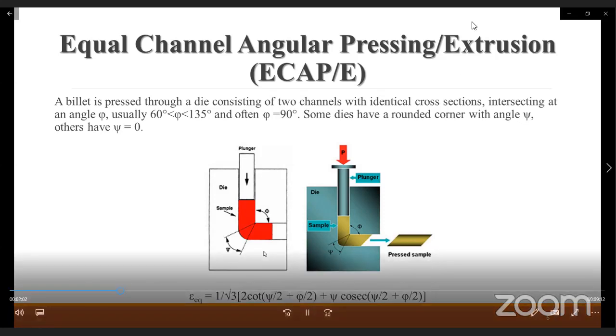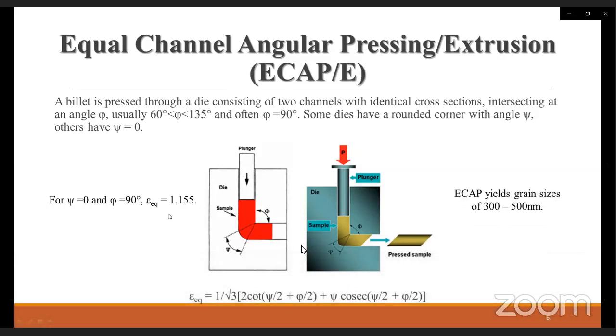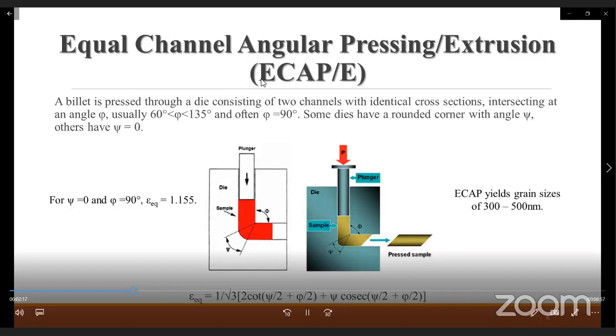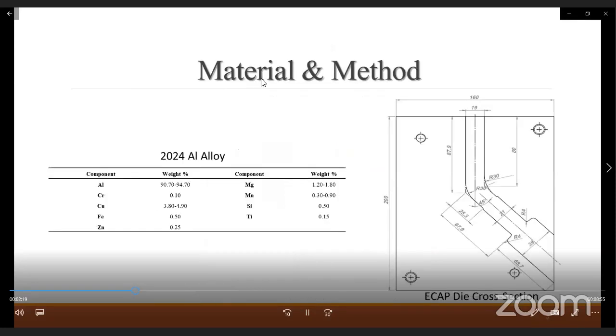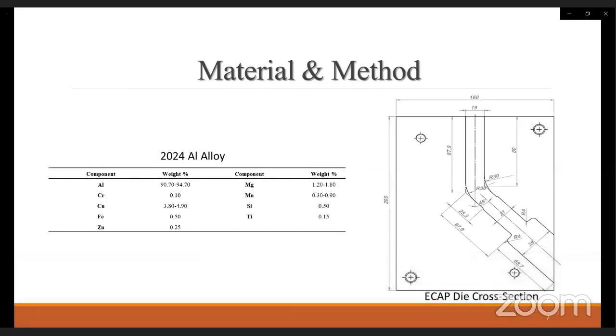And this is the basic strain formula with the angles, and with the 0 and 90 degree values we get the strain of 1.155, and with ECAP we can get 300 and 500 nanometer grain sizes. So for the material and method section, we have used in this study 2024 aluminum alloy.